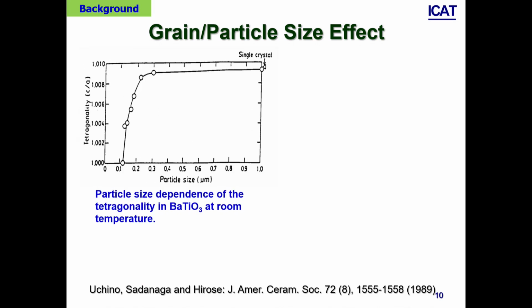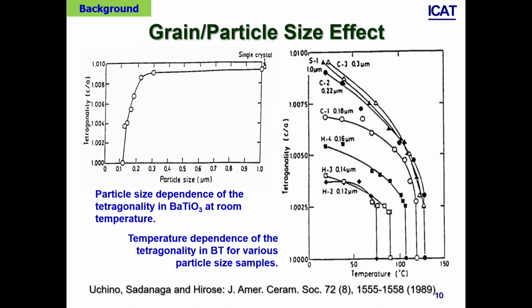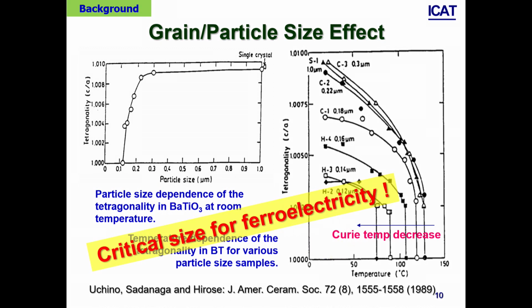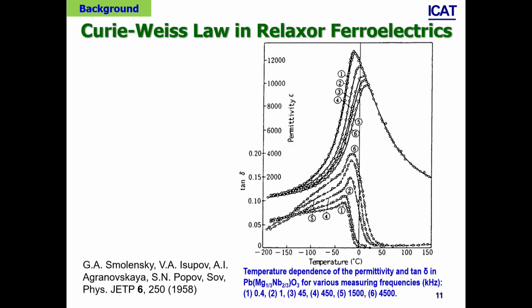Grain size, particle size effect. Probably most of you are familiar with these papers: barium titanate, with reducing a particle size below 0.1 micrometer, the ferroelectricity will be completely lost. So Curie temperature is gradually decreasing with decreasing particle size, okay? So critical size for ferroelectricity.